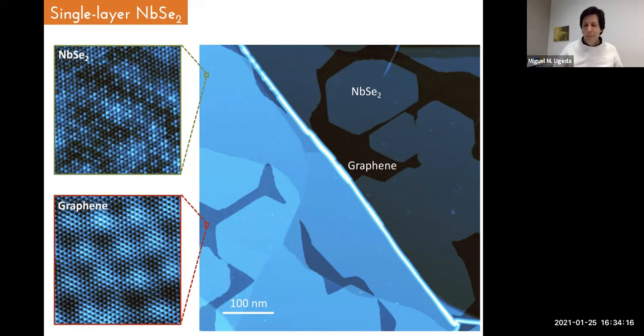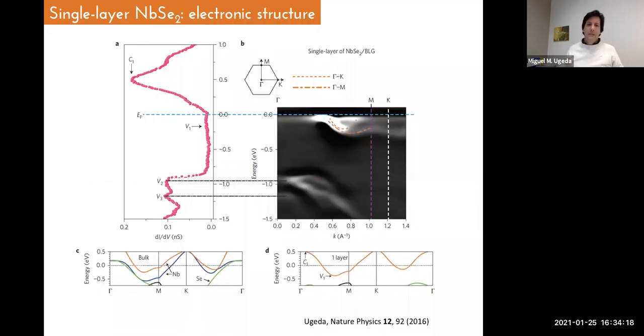Here, this is the typical STM image of our substrate, graphene, showing the underneath reconstructions of the silicon carbide. Okay, so in terms of the band structure, and this is something that some of us did in the past, this system is well characterized, and niobium diselenide is well characterized on graphene. It was predicted that when you reduce the material from bulk to the single layer, the band structure should simplify from three bands crossing the Fermi level down to one band.